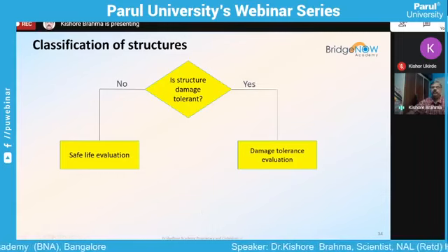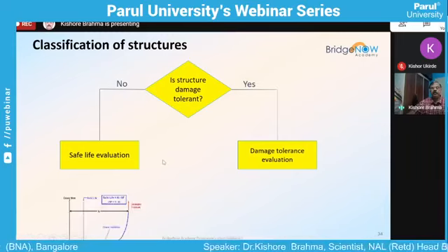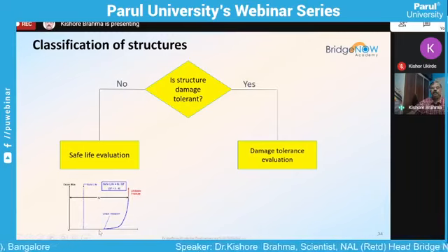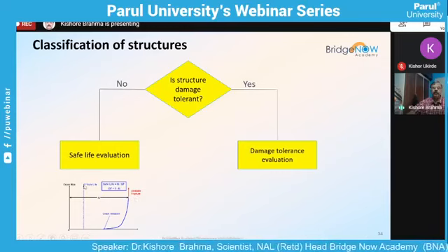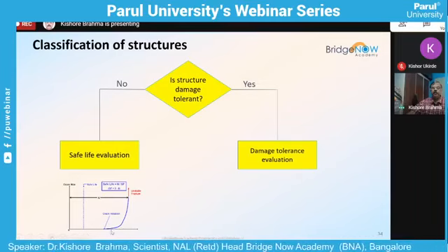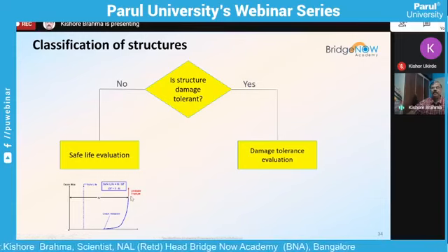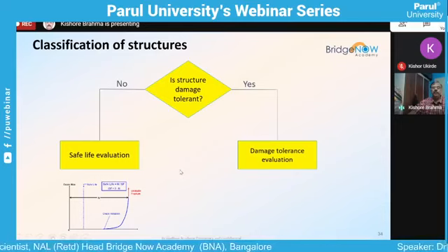So if your structure is not damage tolerant, then one has to go for the safe life, where you have to do some testing and find out the number of cycles, then use a scatter factor of 4. Then that will be the limiting life of that structure. You can see for this example here, if you take a component, assuming that from crack initiation to critical crack takes 1 lakh cycles, and if you use the scatter factor 4, then the life will become 25,000. So obviously, from safe life evaluation, as the name suggests, safe life.